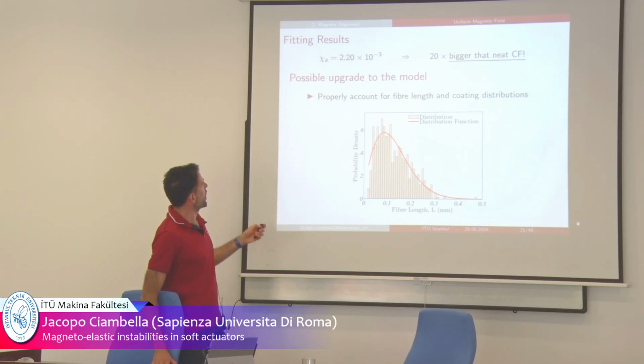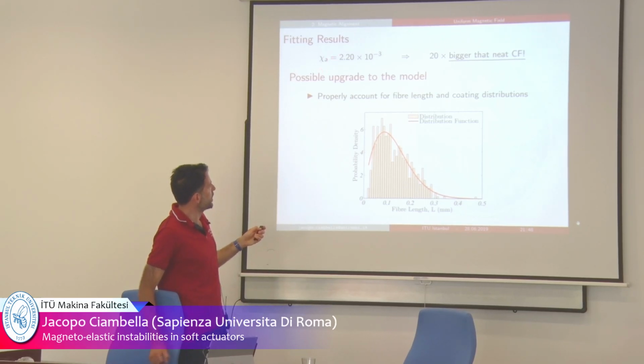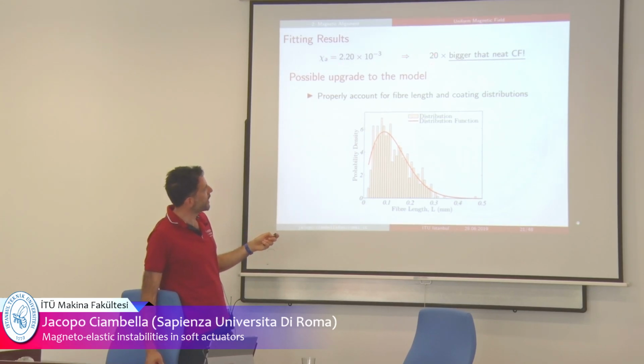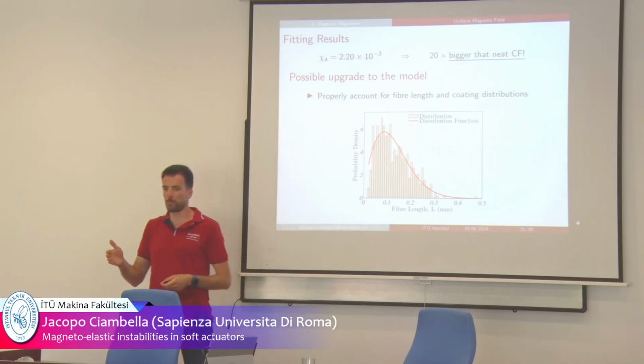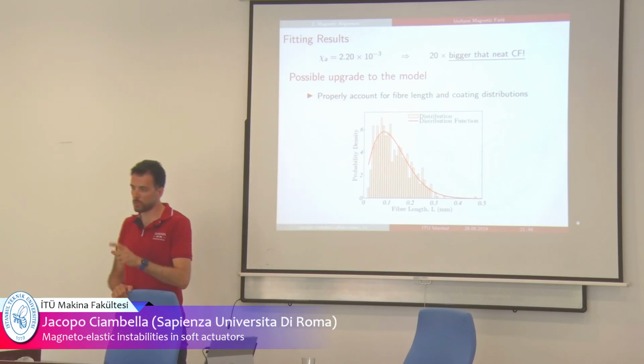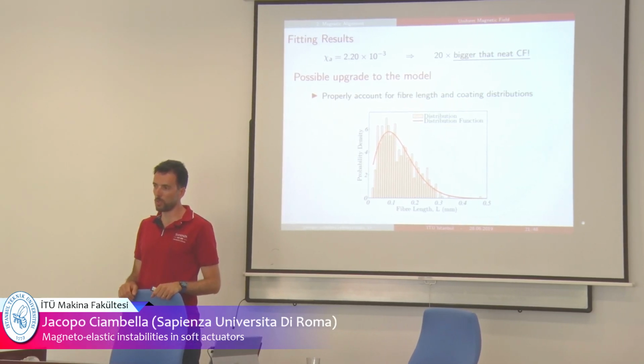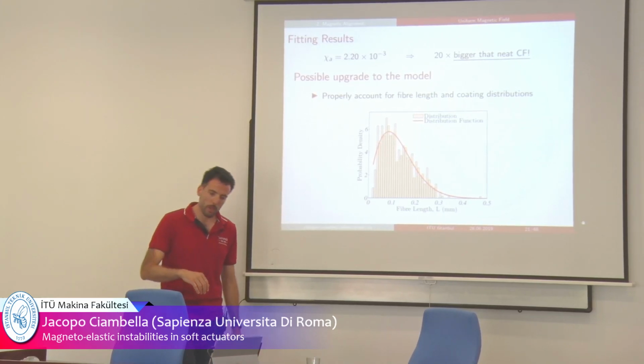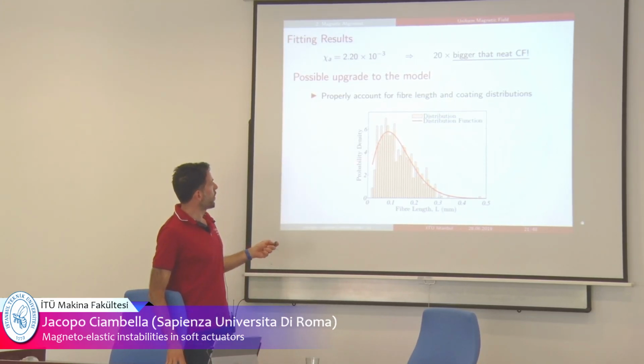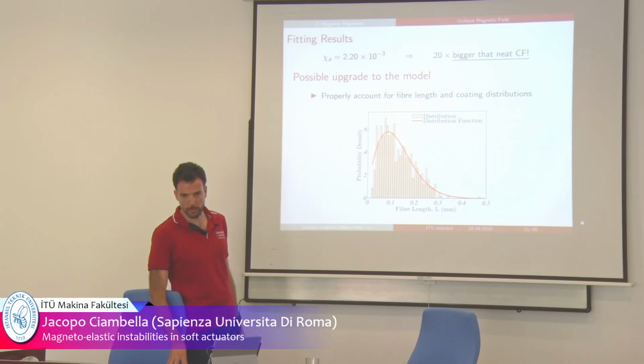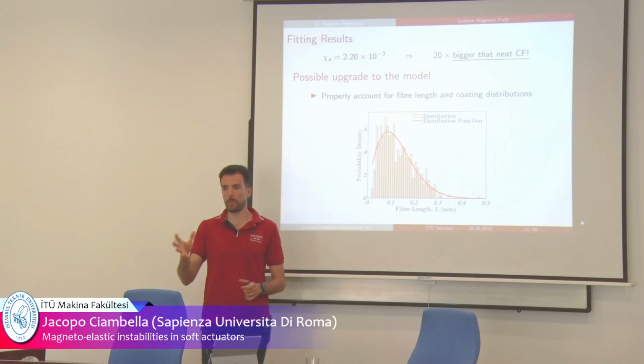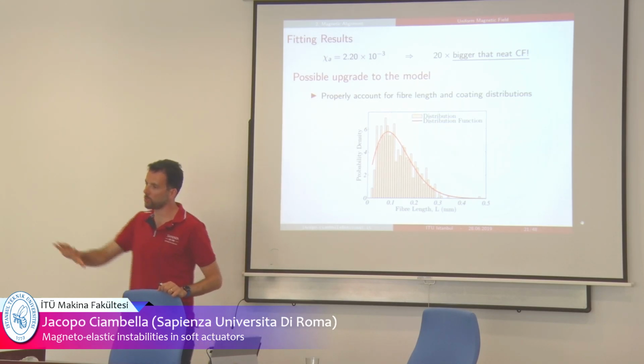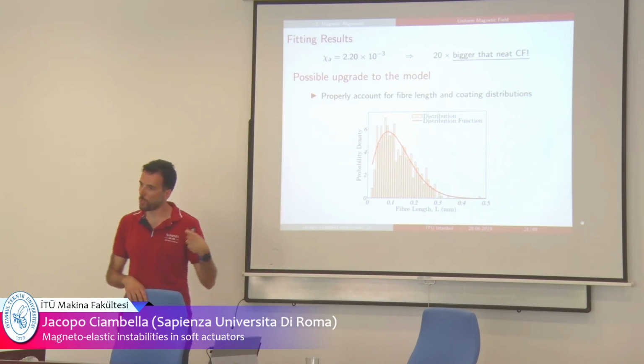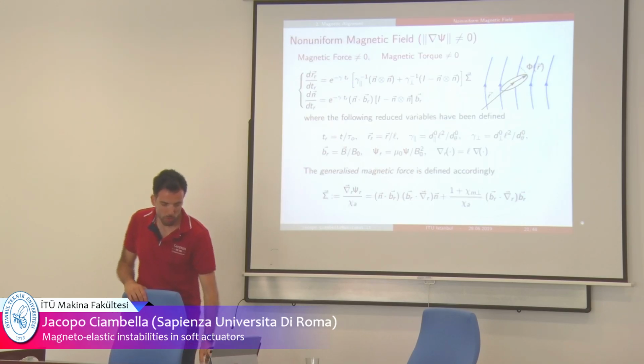And so we extracted the magnetic susceptibilities by fitting those experimental data, and what we observed was that the magnetic susceptibility was almost 20 times higher than standard carbon fiber. But this was expected because these are not standard carbon fiber, these are coated with nickel, which is a very active magnetic material. Okay? Possible upgrades: we didn't consider the distribution of length. All the fibers were 0.25 millimeter, but you have a certain dispersion in the length. And the dispersion affects the orientation time quite drastically. So you can improve this model by taking into account the distribution of length.